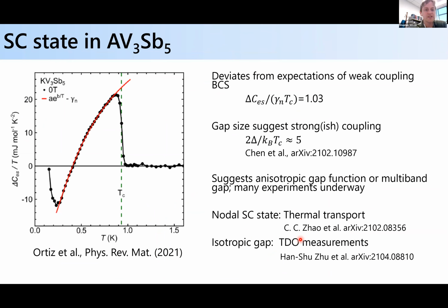So looking at the superconducting state, there's a lot of ongoing work on that. And I would say that there's not a lot of consensus about the nature of the superconducting state yet. I think probably consensus is in the following. If you look at the magnitude of the specific heat jump due to this onset of superconductivity, it's sort of below what you consider the typical BCS model. Basically, if you look at the magnitude normalized by the Sommerfeld coefficient times the TC, it deviates from the expectations of weak coupling BCS.